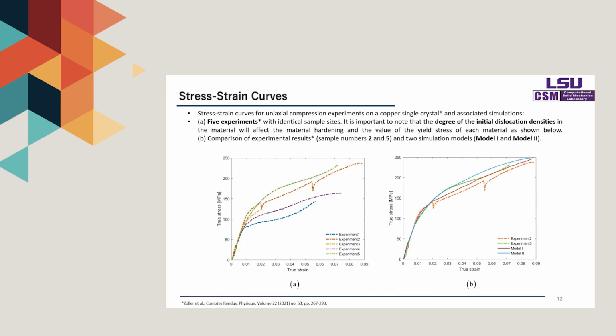Now, figure A illustrates the variation of stress strain curves for the identical sample sizes. It is important to note that the degree of the initial dislocation densities in the material will affect the material hardening and the value of the yield stress of each material.